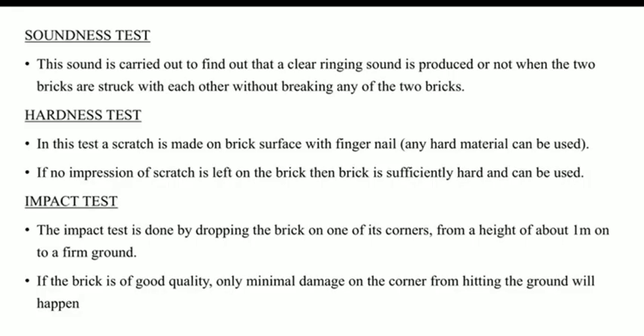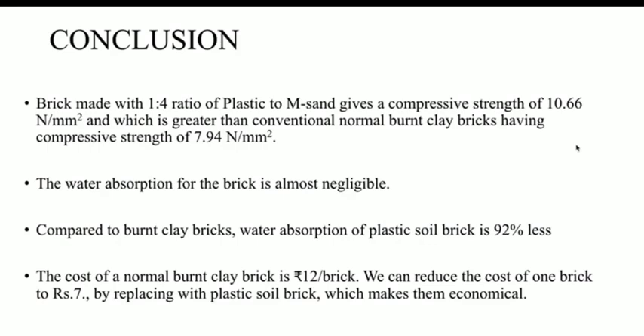Water absorption of the plastic brick is 92% less than the burned clay brick. We also conducted soundness test, hardness test, and impact test. The results obtained were satisfactory for the plastic brick. The cost of a normal burned clay brick is Rs. 12 per brick, whereas the cost of a plastic M-sand brick was found to be Rs. 7, making them more economical. We conclude that the brick made with a 1:4 ratio of plastic to M-sand is more economical than the conventional burned clay brick.